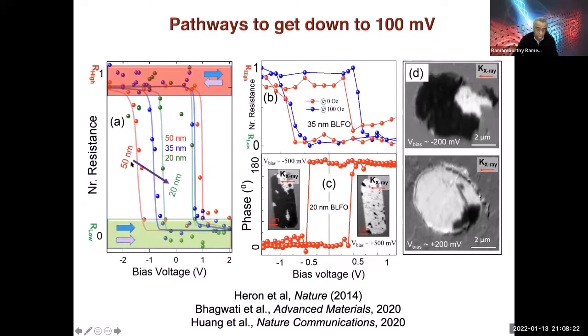And we were able to show that we can go from maybe 1 volt at 50 nanometer thickness to about 500 millivolts at about 20 nanometers. We also did some very rudimentary work, and this is not meant to be robust. We used imaging, again XMCD-based imaging, to show that 200 millivolts may be okay for a 10 nanometer film, but it was not done in a very rigorous way.